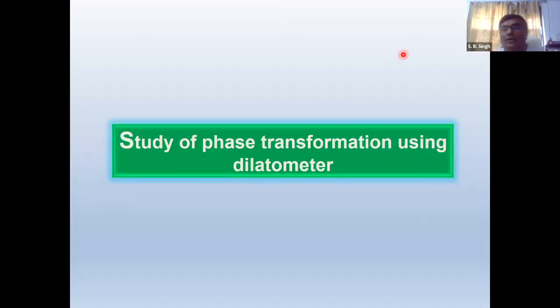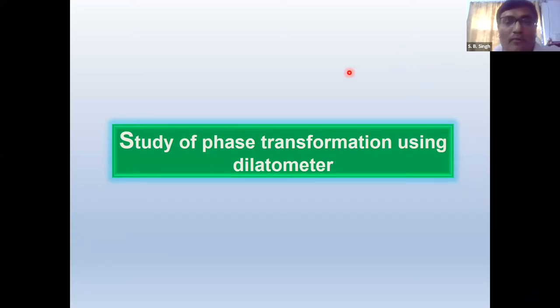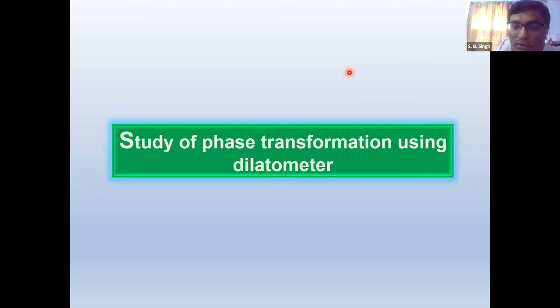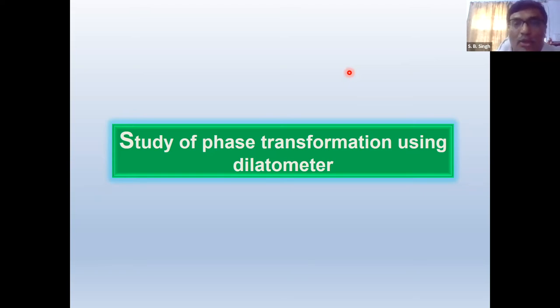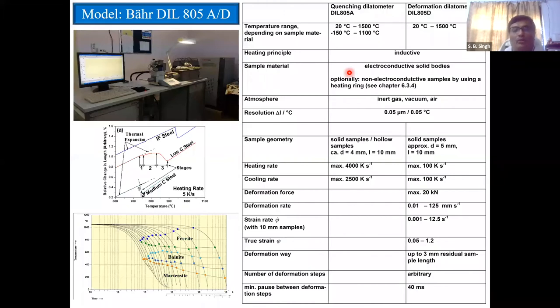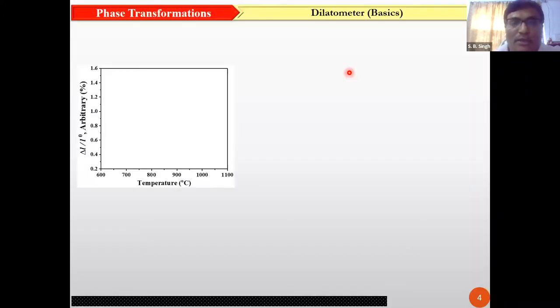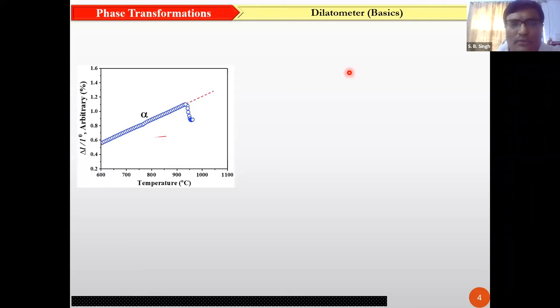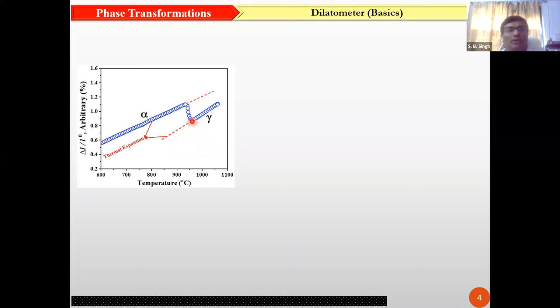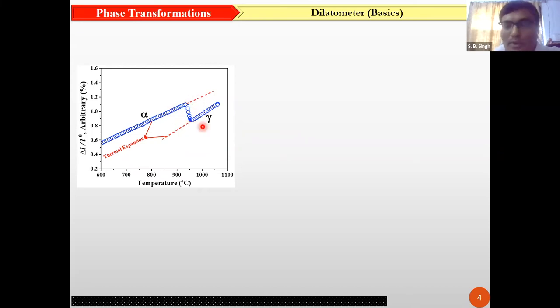In steels especially, transformations can be studied using dilatometry. It is a very powerful technique to determine the transformations and can detect transformations as they happen. This is a typical dilatometry curve — if you cool a material from high temperature austenite phase, this is the kind of behavior we get. Usually it is used to detect the transformation start and finish temperatures, but during the transformation we can quantify and get much more detailed information.